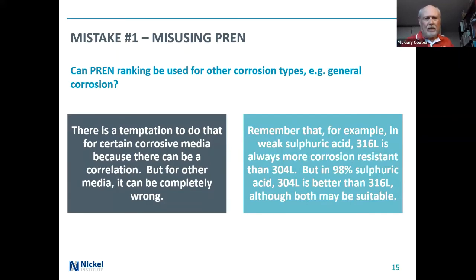But in some media, there is a good correlation. So for example, if we take weak sulfuric acid, 316L is more general corrosion resistant than 304. So it actually works there, even though it wasn't intended to be used that way. But if we take 98% sulfuric acid, 304 is actually slightly better than 316L. Both may be suitable, both may be used, but the PREN number doesn't give anything. In fact, it actually gives a wrong indication there.